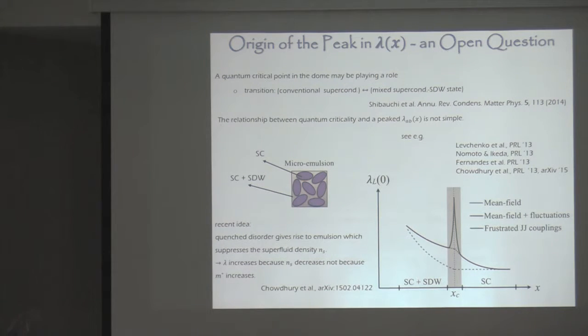But getting a peak is not an easy task. And in fact, this is a pretty recent paper where there's an idea that what gives rise to this peak is an emulsion between these two phases. So they're phase separated on a scale that's not known, but it could be down to nanometers, but it could be much bigger. And maybe these materials are less disordered than other pnictides, where if the disorder is greater, then the scale is smaller, and then this could be a reason. But again, this is under debate. This is a plot from this theory paper.